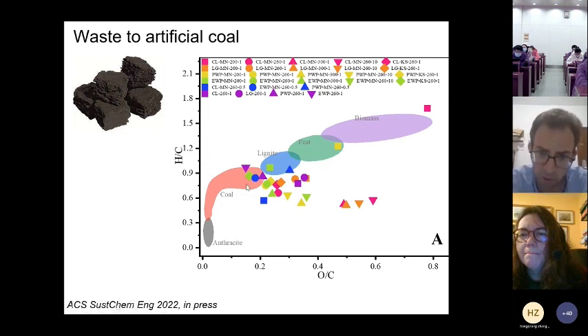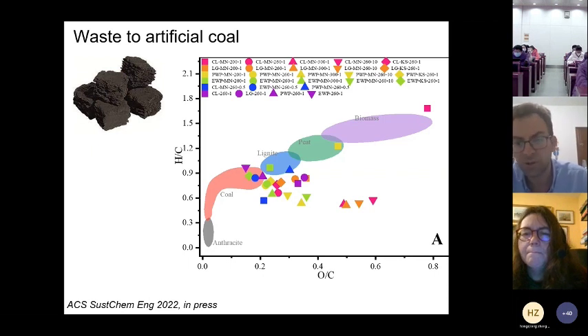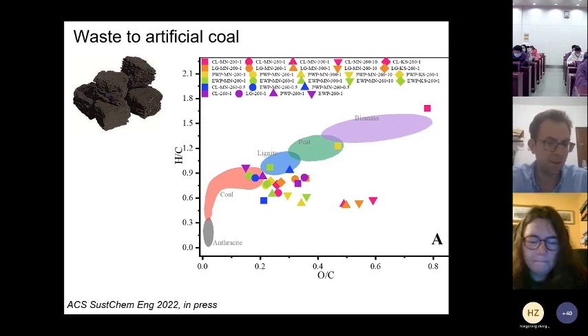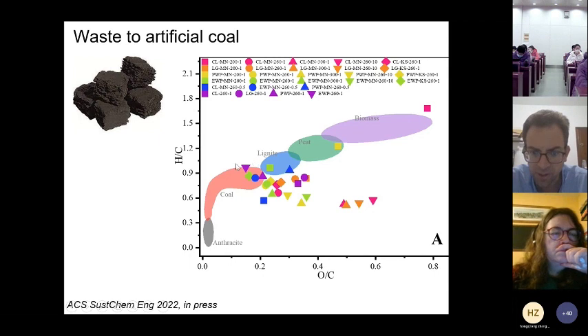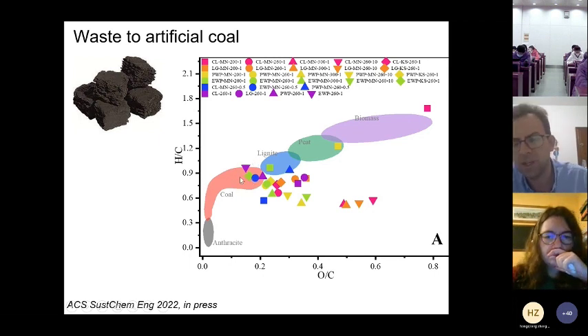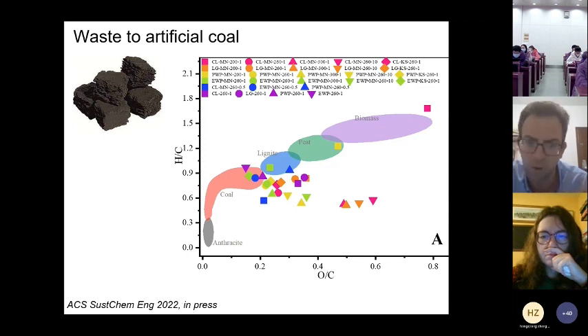And for these particular 4 points that you see in the slide, in which hydrothermal carbonization was performed at 260 degrees C and with the addition of an important oxidant that plays the role of removing and degrading some of the proteins that are in sewage sludge and pushing this hydrothermal carbonization towards a highly qualified material, you see that we were able to obtain the so-called artificial coal with a calorific value that resembles very much that of coal. And this is close to 85% of the calorific value and of the properties of coal.